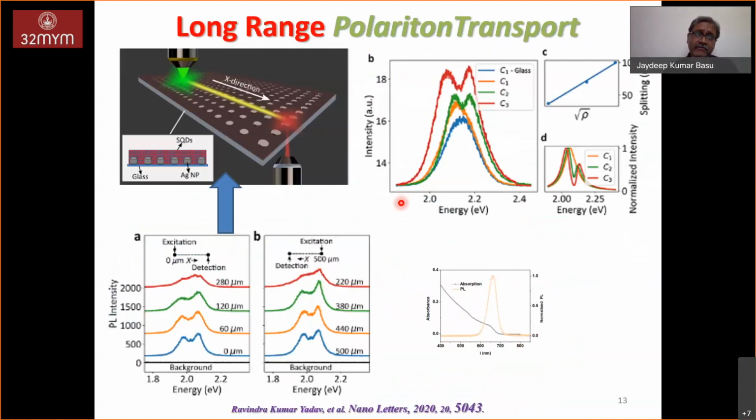So the first part, what we observe when we create this, now how do we detect these modes appearing? This is what I showed when we were looking at isolated dots. Now when you have a compact array, and you increase the concentration, then you start seeing this splitting. The two modes which are emerging correspond to the hybridized modes, which appear as a result of the strong coupling between the excitons and this lattice mode, and it nicely shows this behavior because it scales with the concentration.